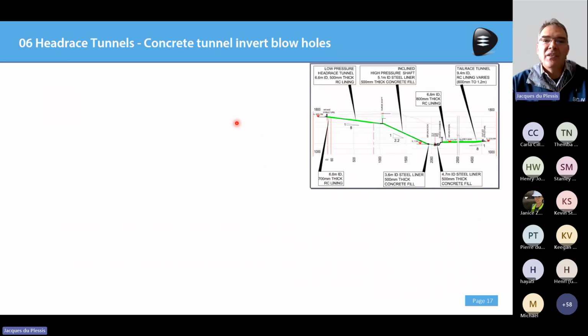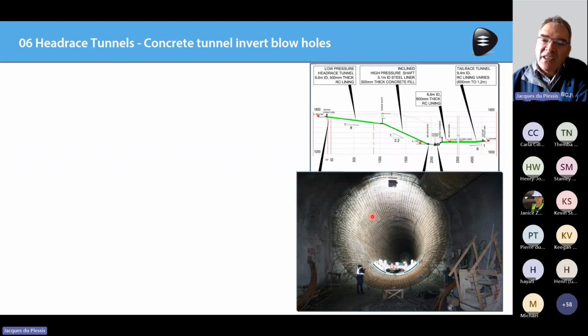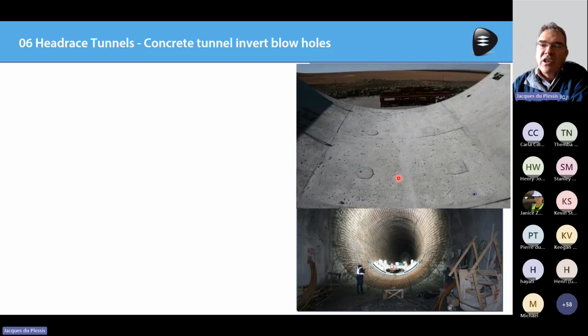Now going to the tunnels, the headrace tunnels, and in particular, the low pressure headrace tunnel. So that first kilometer over there, 1 in 8 slope. Important to keep that in mind. So the contractor decided to do a split shutter for that section of the low pressure tunnel. So he would have a shutter on the invert of the tunnel, place the concrete up to there, and then bring the top shutter for the top stage of the concrete. So he started a full-scale trial, and he just couldn't get rid of these blowholes.